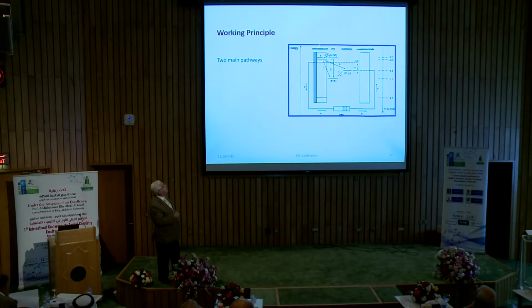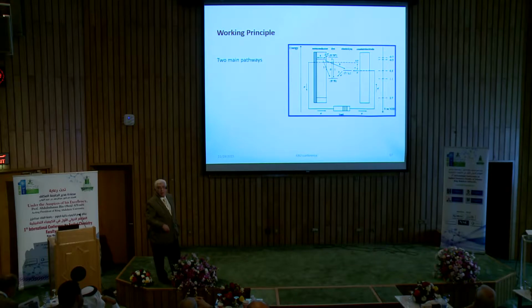This is a solar cell, mesoporous titanium oxide semiconductor, and this is a counter electrode, and this is electrolyte. In the electrolyte, there is a dye. The problem starts with the excitation of the dye. Once the dye absorbs light, it gets excited, an electron in the LUMO, instead of returning back to the HOMO and getting recombination, is injected into the mesoporous film and in the outer circuit to the counter electrode. So you create a current. This is the idea of the dyes inside a solar cell.